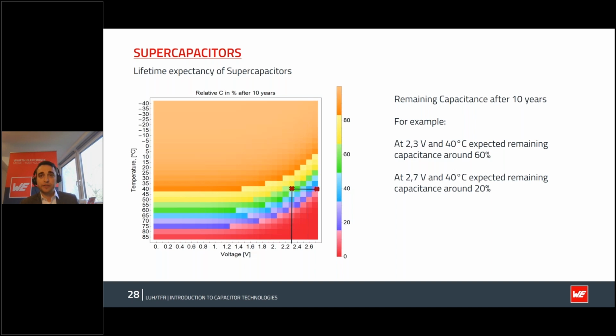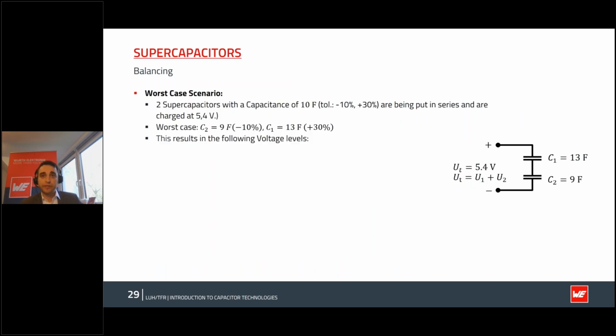As the voltage is limited and a lot of times you want to use at least 5 volts for your application, many people tend to use them in series. And there you have to calculate for the worst case because they have a production tolerance of minus 10% and plus 30%. And this could cause an overvoltage if one has a higher capacitance value than the other. So for the worst case here, we use the max tolerance and the minimum tolerance. And then we have this formula where you can calculate with the 5.4 volt for UT. And then you can calculate the overvoltage of the capacitor with the lower capacitance is over 3 volts.